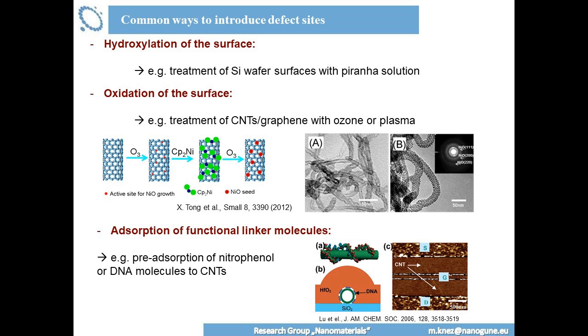So you can use this substrate to bind your molecules to those local sites which you oxidize, and then start growing materials on those spots. It's a sort of approach for also area selective ALD.